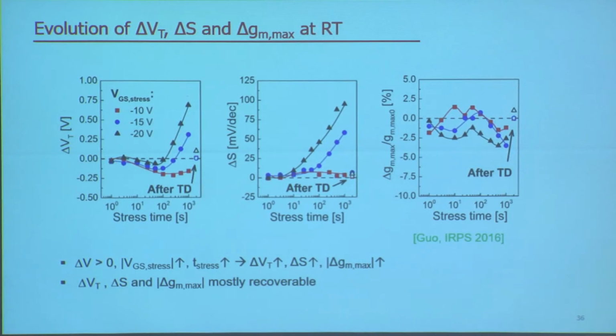So what we do first is, again, look at room temperature, and we change the stress voltage from -10 to -20 volts, and we again trace the stress time evolution of the three parameters: delta VT, delta S, and delta GM max. And you see that even though at the beginning there's a slight negative VT shift, which we have just discussed, after some stress time, they turn around and become positive. This positive VT shift increases with the stress time, and also increases with stress voltage. And accompanying that, we also see an increase of the subthreshold swing and a slight decrease of maximum transconductance. And at the end of the experiment, after thermal detrapping, all the device degradation is completely recovered.